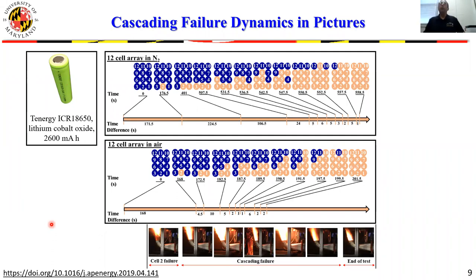All right. So we've done this in nitrogen and air because we try to better understand how the flaming combustion of the battery materials would affect that propagation of the thermal runaway, or what we refer to here as cascading failure. What we found, in essence, one of the key findings, was that you don't really need air to propagate the thermal runaway through the array.